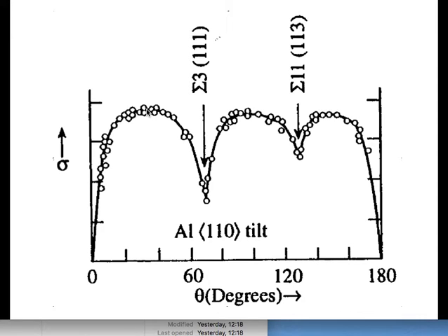Where we derive the equation giving us the interfacial energy as a function of dislocation density. But then we are getting coincidence, and therefore you have a cusp, and then the Read equation kicks in again, but relative to the sigma 3, okay? Not the sigma 1, sorry, where everything is coincident, that means you have a single crystal, all right? And so on. So all these segments are like the Read equation, but applying from a different starting point. Okay, so we now can deal with not just small misorientations, but large misorientations as well.